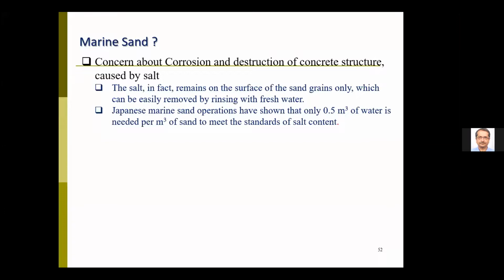So what people have tried to do, even in Kerala, is to excavate sand. I don't know if you know, the sea level was much lower several million years ago. So the rivers were flowing a larger distance into the area which is right now occupied by the sea, which means the river bed is there under the sand of the sea in those coastal areas. People are planning to excavate that particular sand, which is about 5 to 10 meters below the existing sand bed of the sea, and use that sand, which has the same gradation as the river sand, because those were original river beds. The only problem is salt, which can be washed.